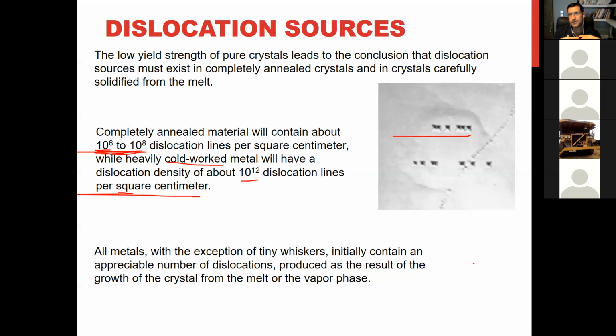In some metals it is not easy; we call them whiskers. Whiskers are very tiny metals that we can fabricate by melt spinning or some special method, like from vapor phases. That type of metal can be dislocation free. Other metals, from common manufacturing processes, all have dislocations from the solidification, and we cannot avoid these dislocations in metallic materials. In all of them, we have dislocations.